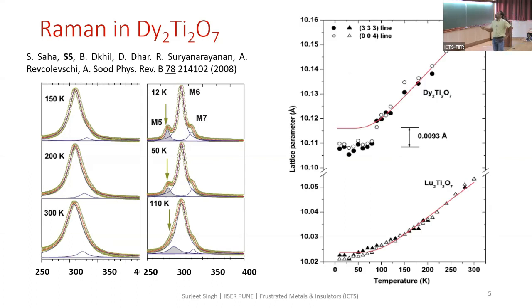And to really nail it down, we measured the temperature dependence of the lattice parameter, and you see that there's a clear discontinuity around the same temperature where the new mode appears in the Raman spectra. So this clearly shows that this compound Dy2Ti2O7 has a subtle structural change which happens around 100 Kelvin. It may not actually have any effect on the spin ice ground state, because the spin ice is determined by the position of dysprosium ions and the spins, but it may change the crystal field excitations slightly because of the displacement of oxygen ions from their regular position.